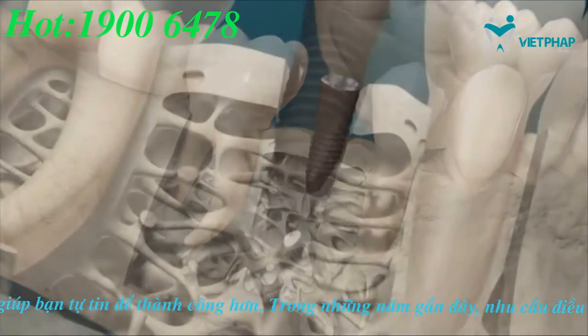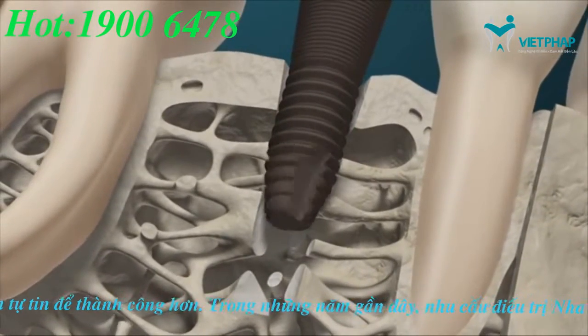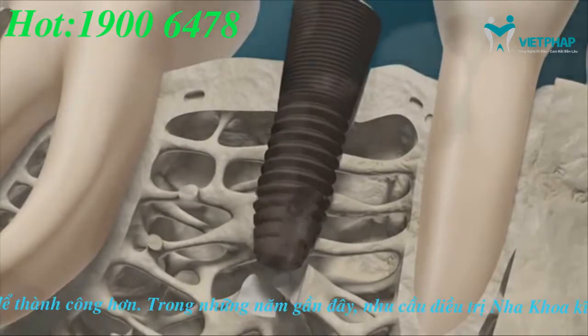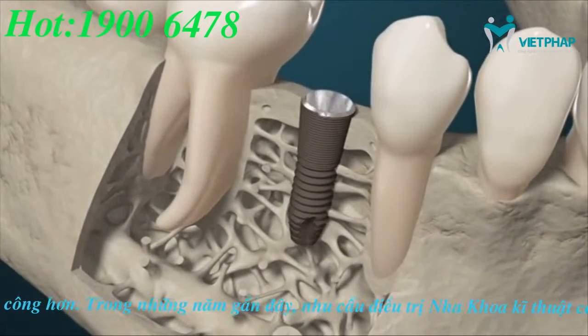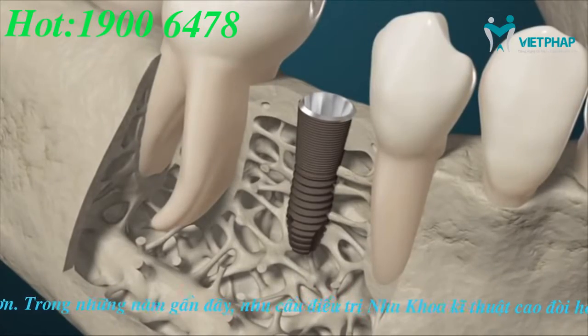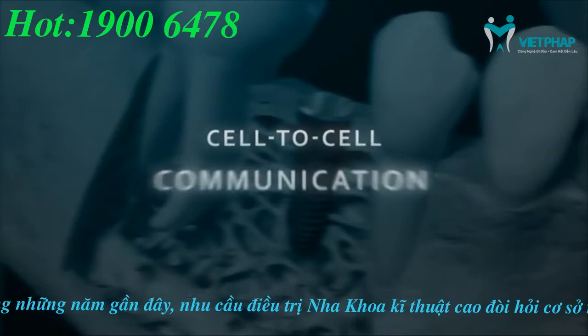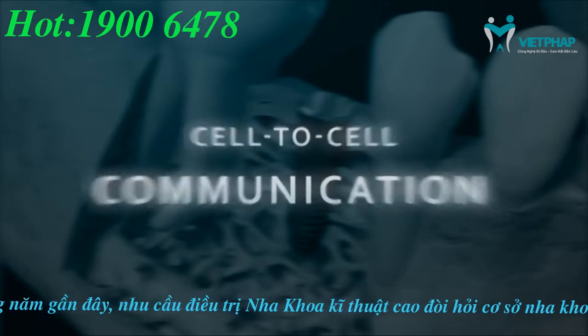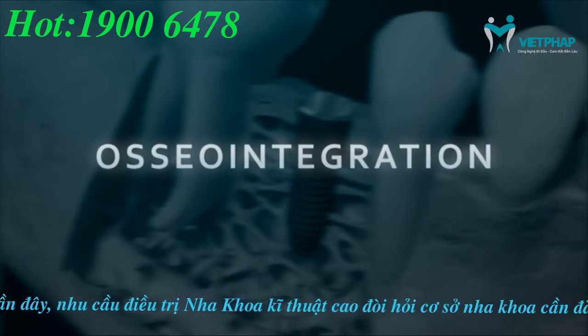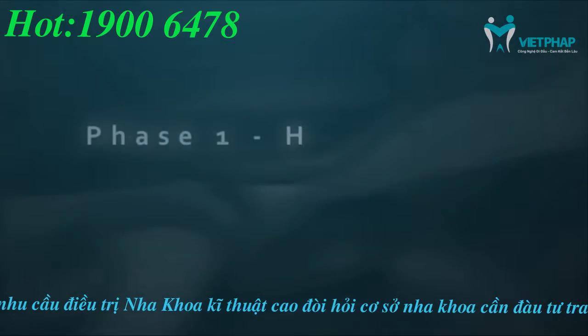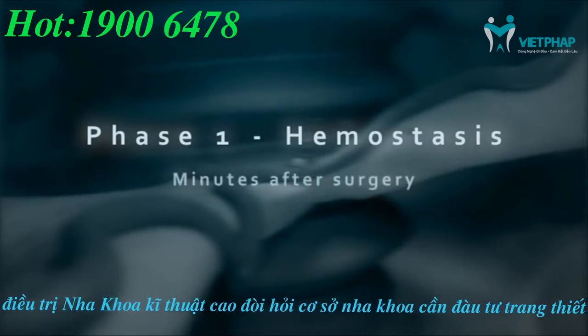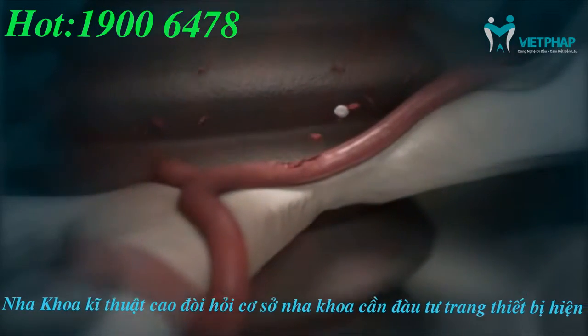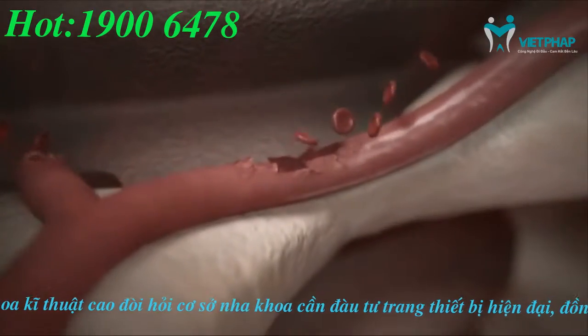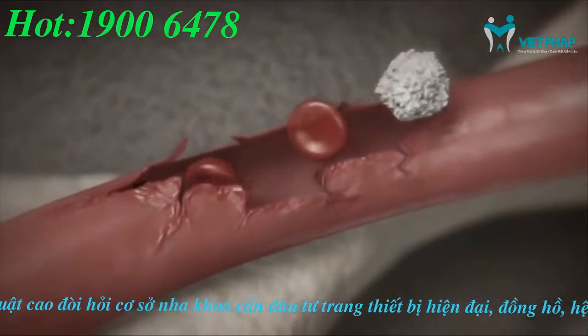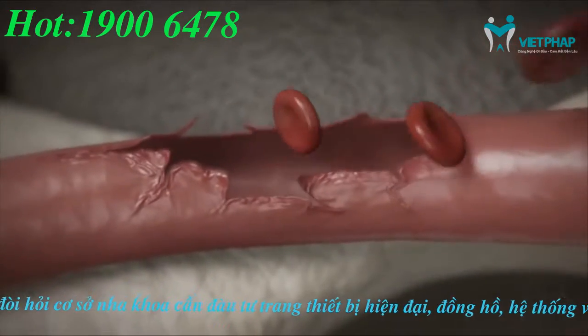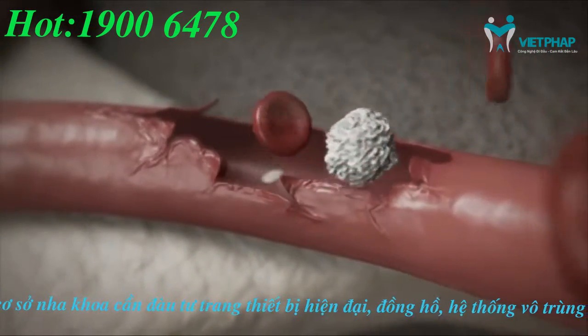Osseointegration, or secondary implant stability, requires a highly complex sequence of additional biodynamic processes. This is facilitated by finely tuned communication between the main actors of wound healing, the cells. The blood immediately perfuses the surgical site, providing the cues for subsequent healing. Within seconds or minutes, ions and serum proteins such as albumin, fibrinogen, and fibronectin begin adhering to the titanium surface.